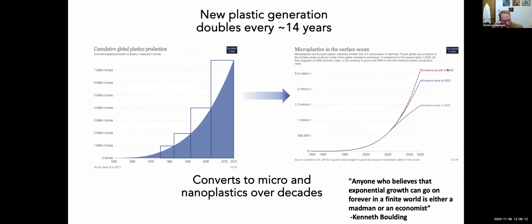So this is really the global problem. We've been generating and using plastics for about 50, 70 years, thereabouts, and it's been at an exponentially increasing rate. The doubling rate of plastics generation is about every 10 to 15 years. And it takes about 30 to 40 years for those plastics to degrade into micro or nanoplastics.